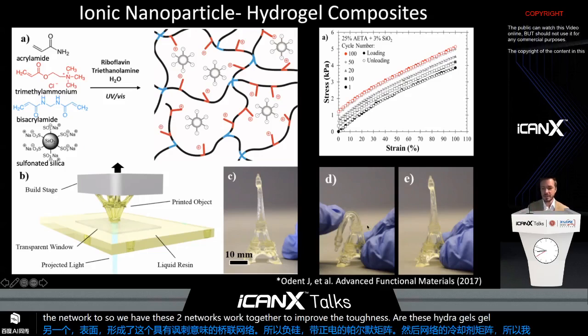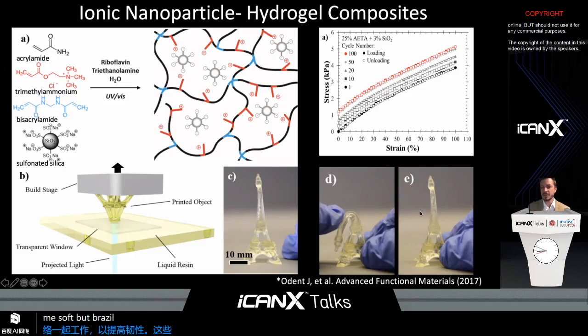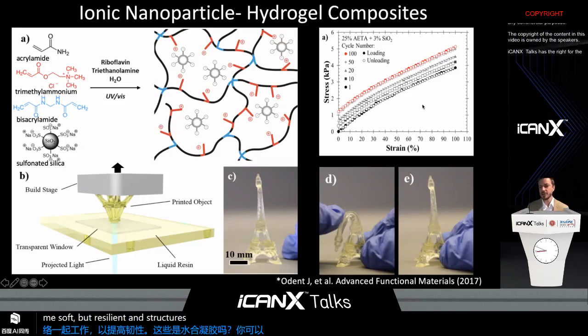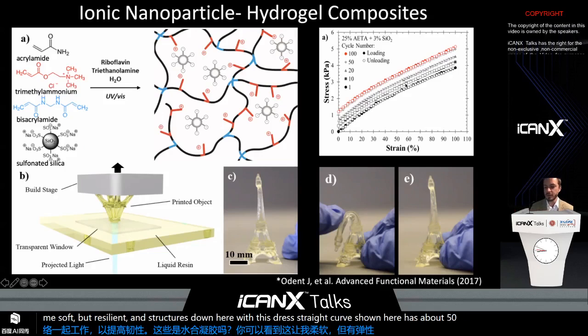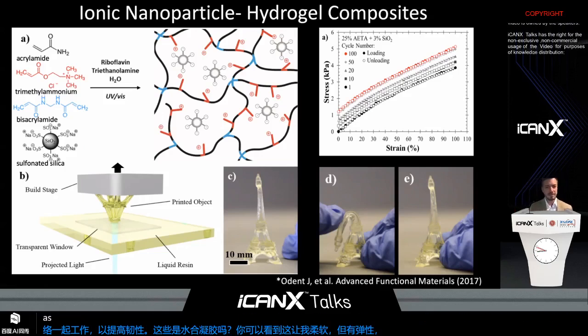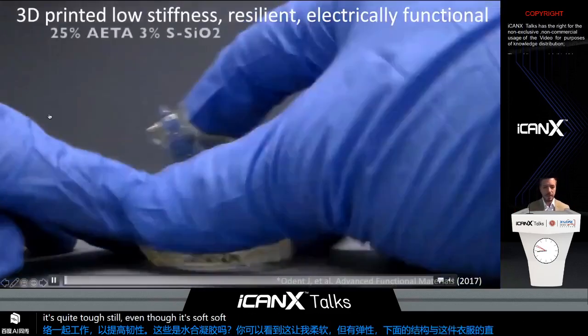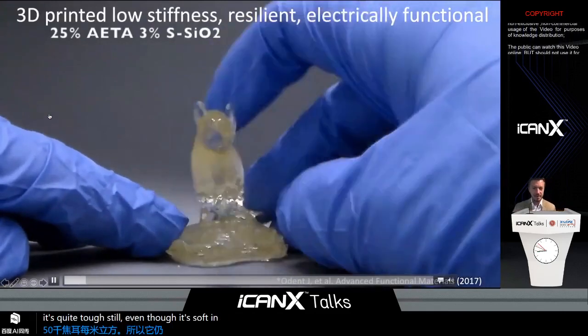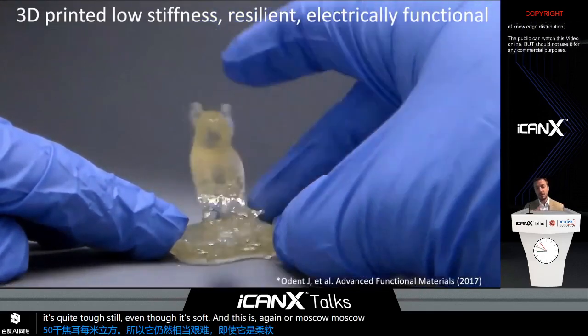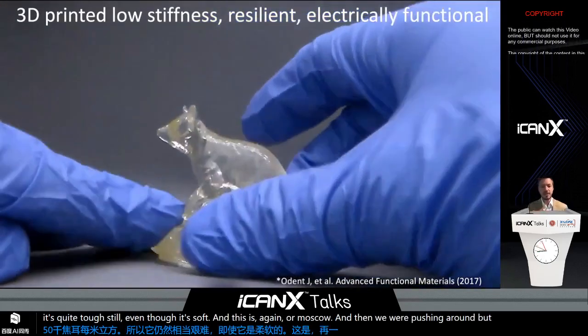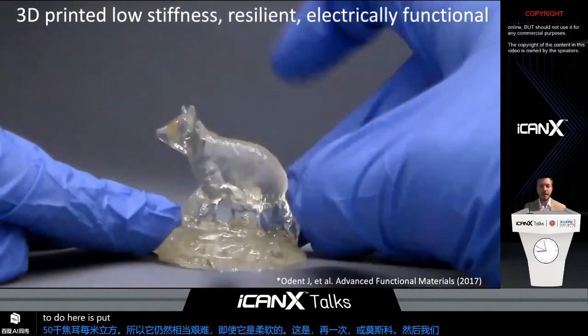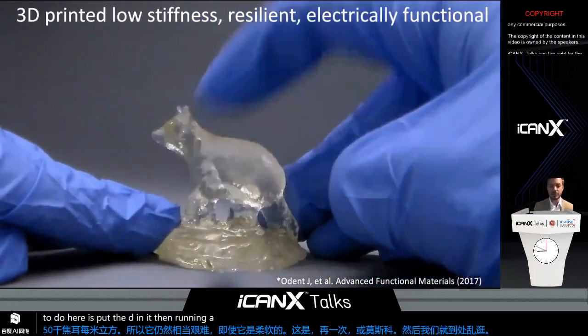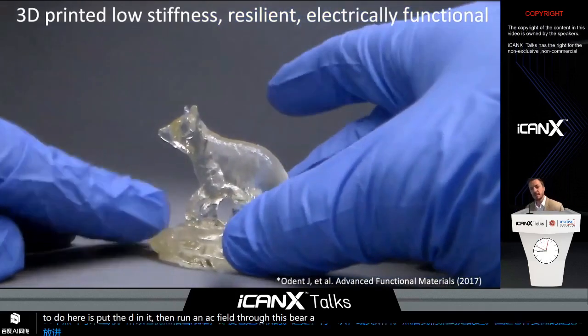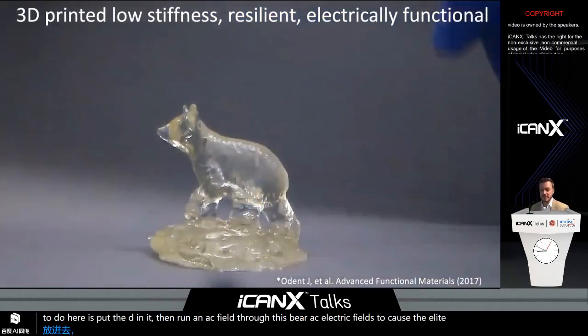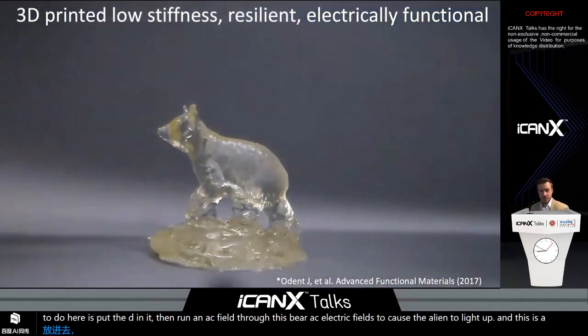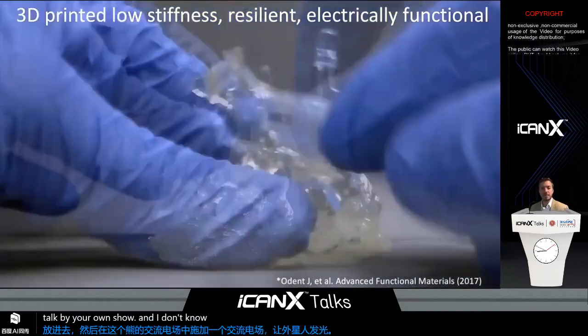You can see us making these soft but resilient structures down here with a stress strain curve shown here. It's about 50 kilojoules per meter cubed. So it's quite tough still, even though it's soft. And then this is again our mascot. And then we're pushing it around, but what TJ is going to do here is put an LED in it, and then run an AC electric field through it to cause the LED to light up. And we saw a talk by Jiang Shuo on ionotronics, and this is one example of it. It's just printing it.